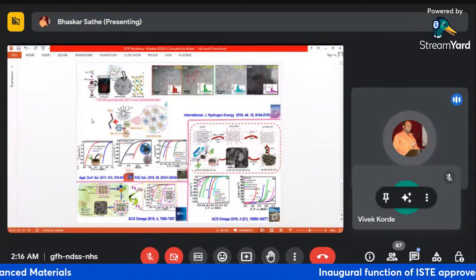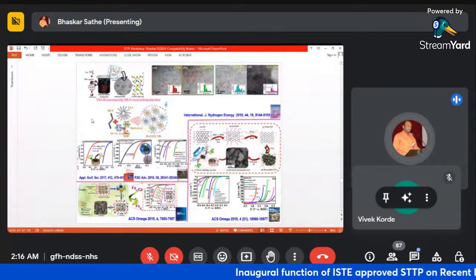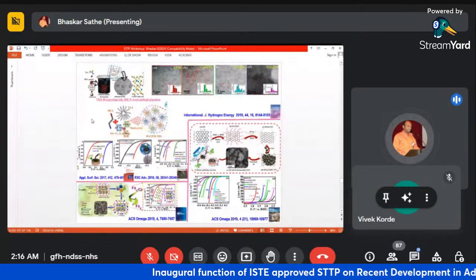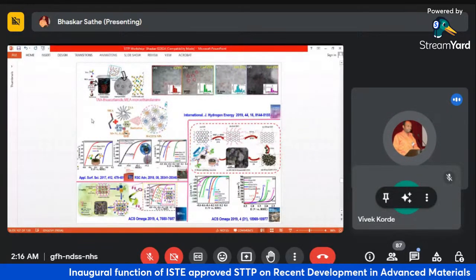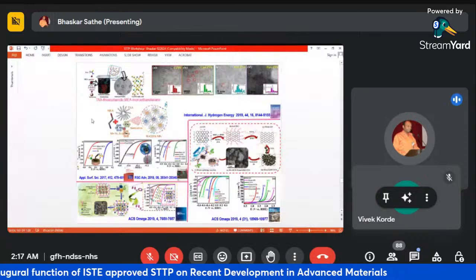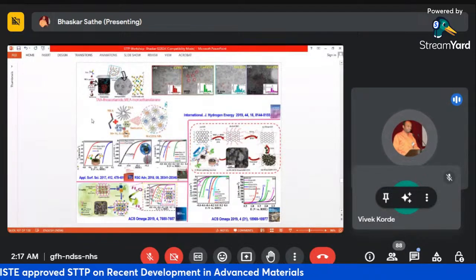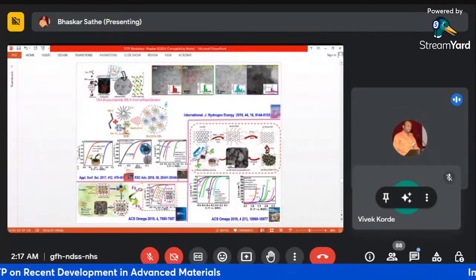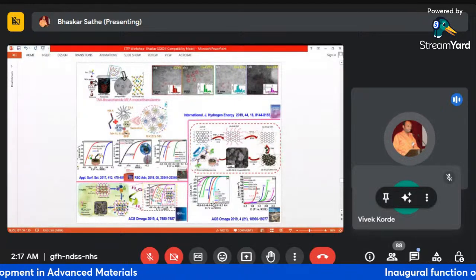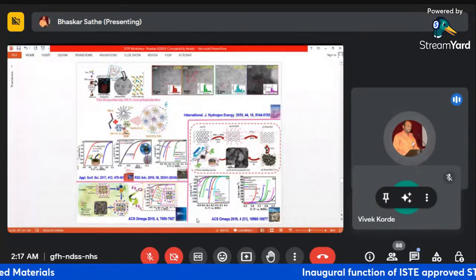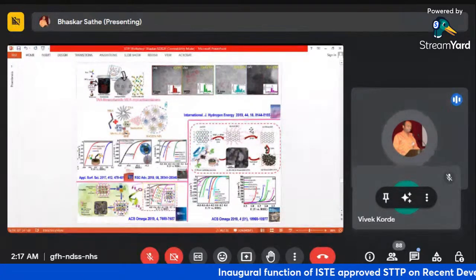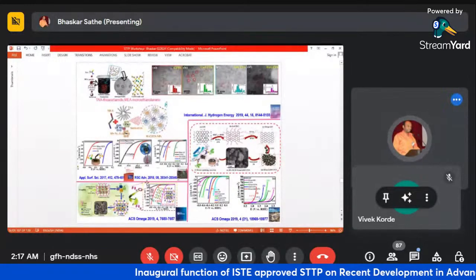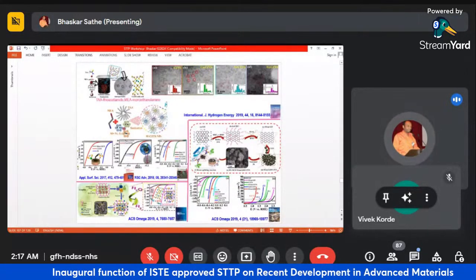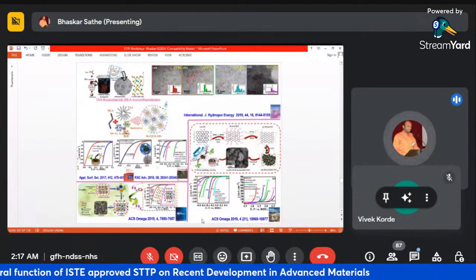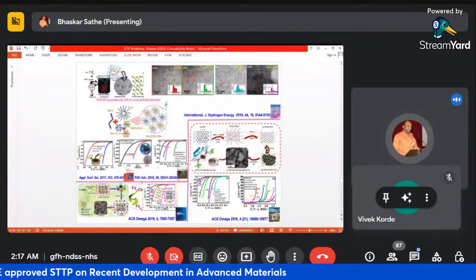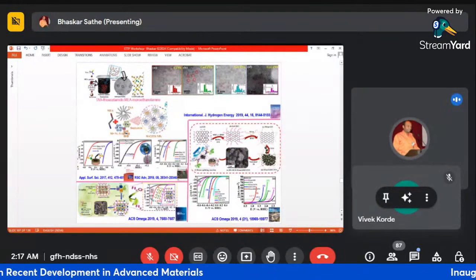Another system where multiple components together, like cheaper materials zinc, tin, and sulfur, we have modified the surface, and we have used that for certain applications like HER and OER. This bifunctional response has come, and this is further coupled with the nanoparticle on the graphene, with amine functionalization. So multiple modifications result in further optimization.